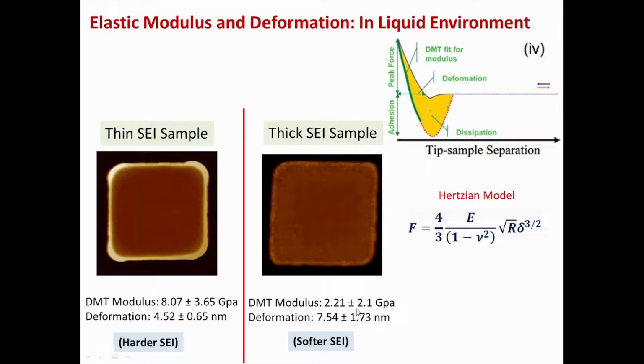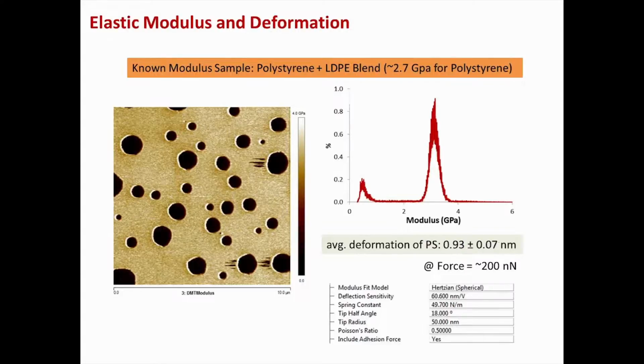What you can see is a DMT modulus of almost 2 GPa for the SEI on the thick SEI sample. What we guess is that this number is reporting mostly the organic character of the SEI on the top surface. The thin SEI sample is giving some of the inorganic character of the SEI layer, which is harder compared to the more organic character. Another thing to note in PFQNM measurements is that you have to make sure that the measurements are right.